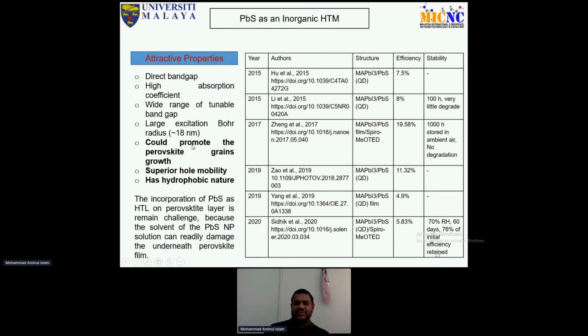That means the grain size could improve the perovskite quality. They also use lead sulfide, and it has superior hole mobility, which is very important for increasing the VOC and fill factor. Another important thing is its hydrophobic nature. That means it repels the moisture, it does not attract it.